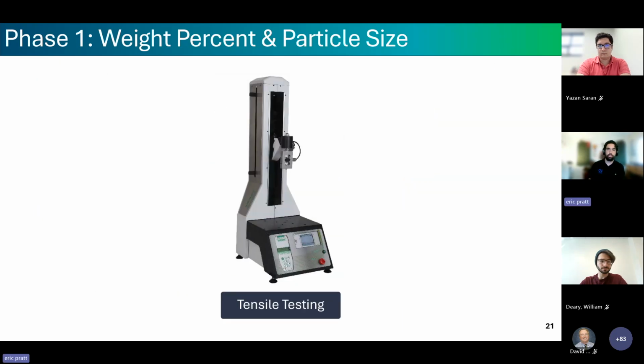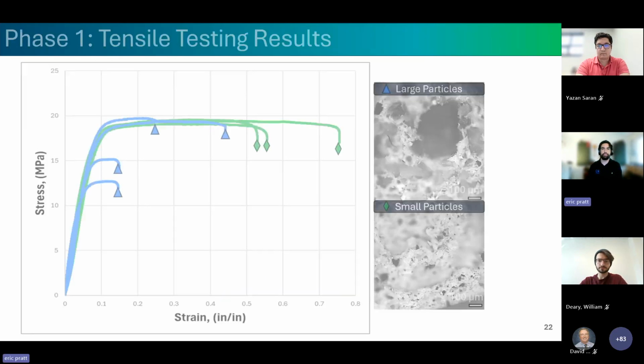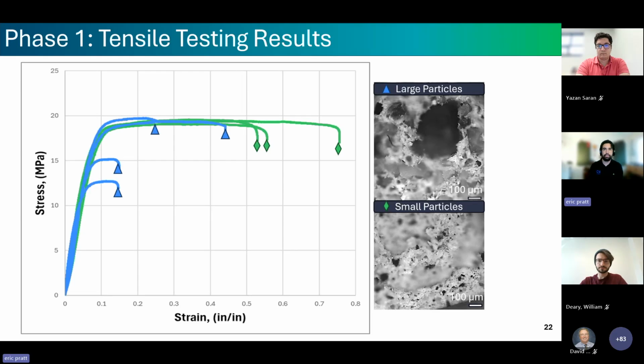So with that context, let's go through some of our actual results, starting with tensile testing. The tensile test data gave us a pretty clear visual story about particle size. Larger particles, shown here in the blue markers, as well as the upper image on the right, consistently failed at lower strain. The mechanism is pretty straightforward here. Under loading, the interfacial bonds between the particles and the matrix break, and a void nucleates right at that interface, and it grows until the material fails.